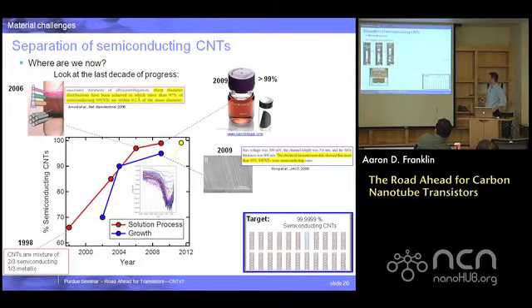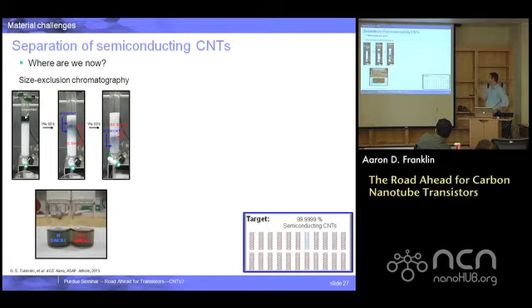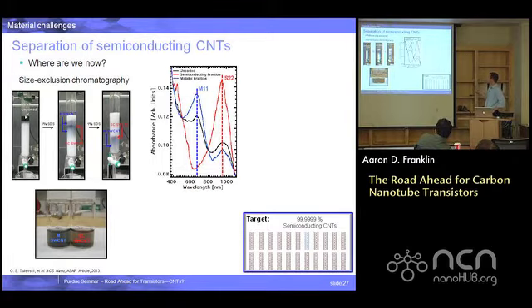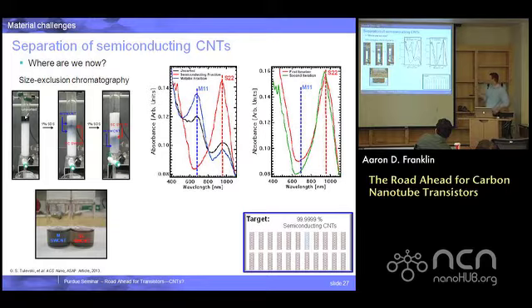But the problem with it is, I guess I have it on the slide after this. Oh, no, here it is. This is the problem. The way that they determine that is using something like this UV vis spectrum. And you tell me if you can tell how high that peak is down here in the red. Can you see how high that guy is? I don't know. You say, oh, give me the numbers and maybe I can tell. Good luck. It's not easy to tell. And that's why 99% is the best we can tell you from UV vis. It could be 99.99, but there's no way we can tell by how small this peak, which shows up when metallic nanotubes are present, is compared to the semiconducting.